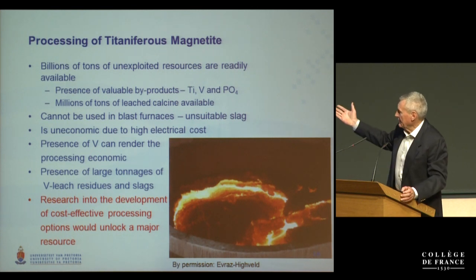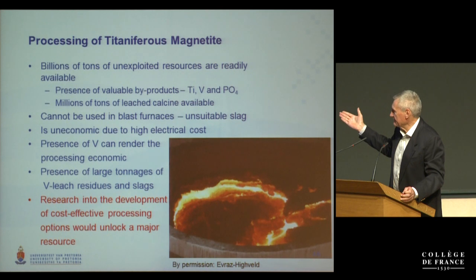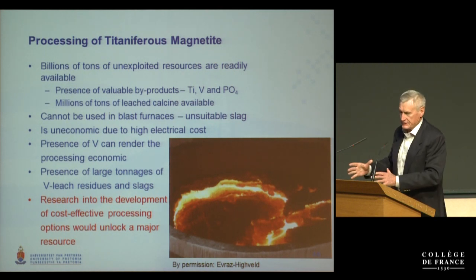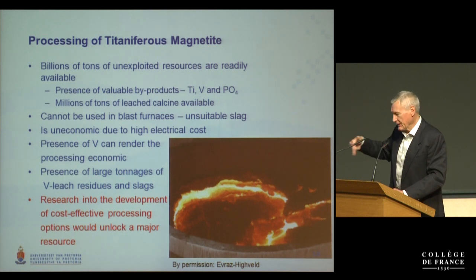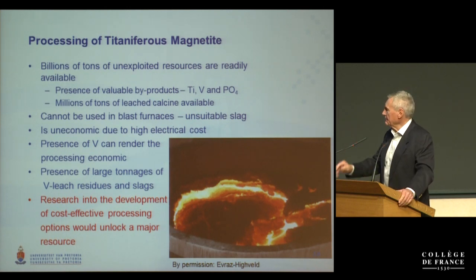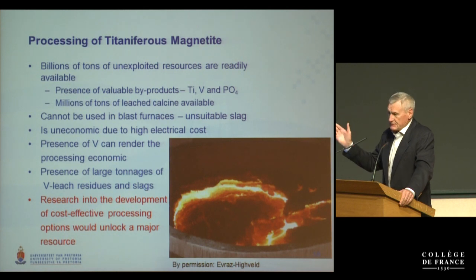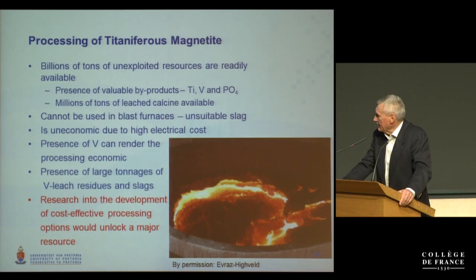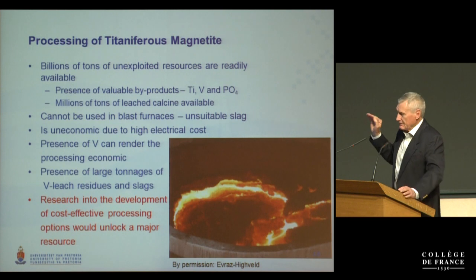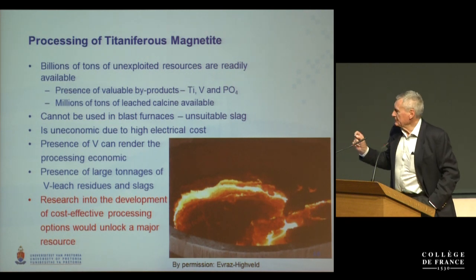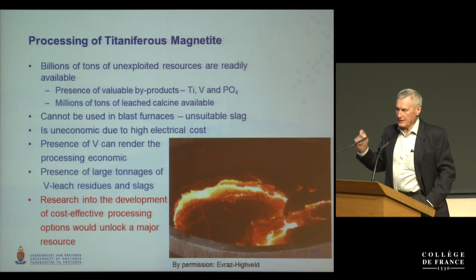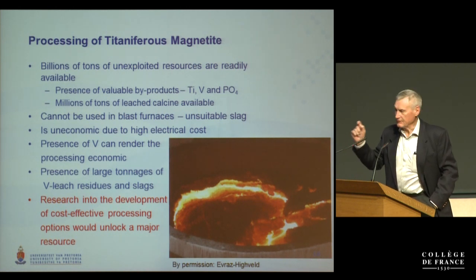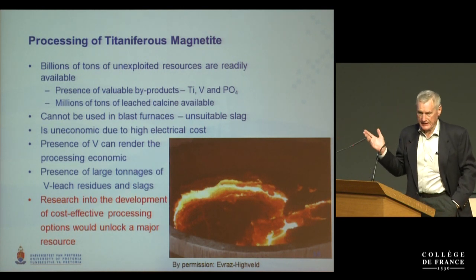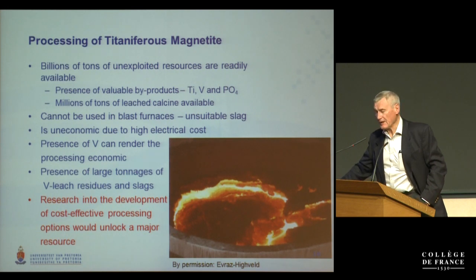But this is an example of a vanadium-rich slag containing about 25% in a slag ladle, which is where the liquid steel is tapped and then oxidized. And this is the present production, apart from also alkaline treatment and leaching. But there is a great need to use this material in an optimal sense to recover not only iron, but also titanium and vanadium. Vanadium content can be up to 2% in the ore. And there are huge resources available.